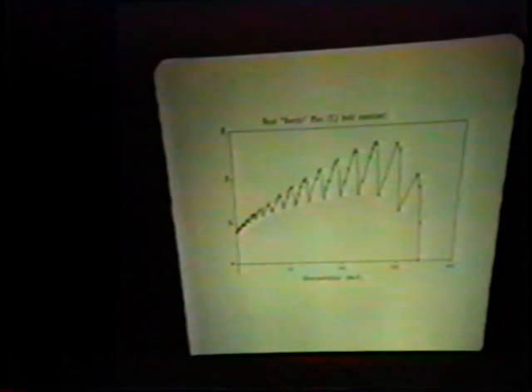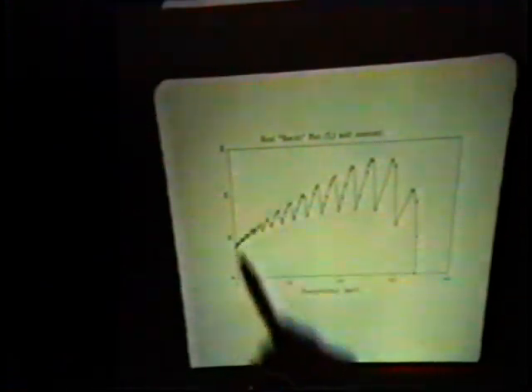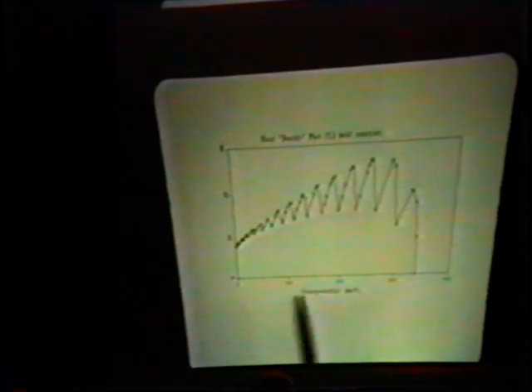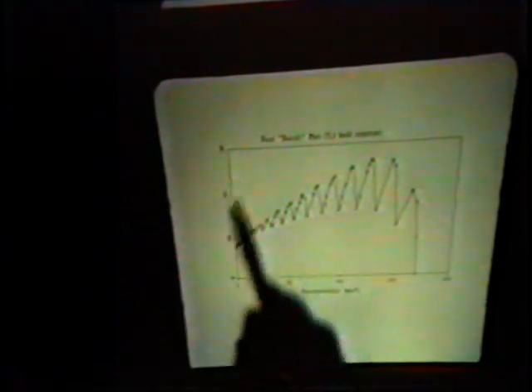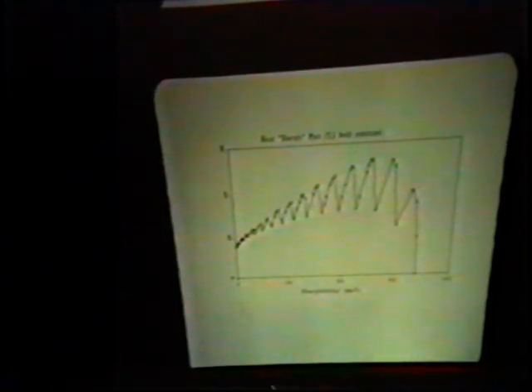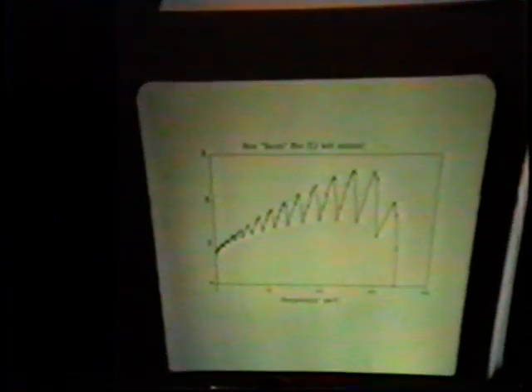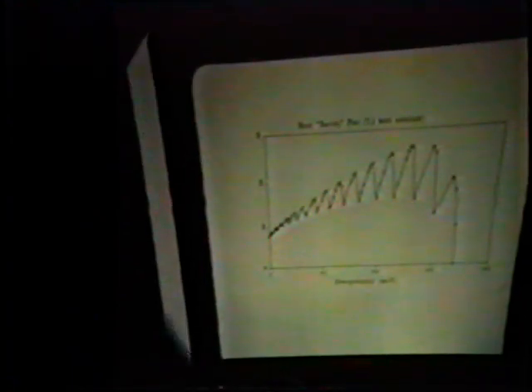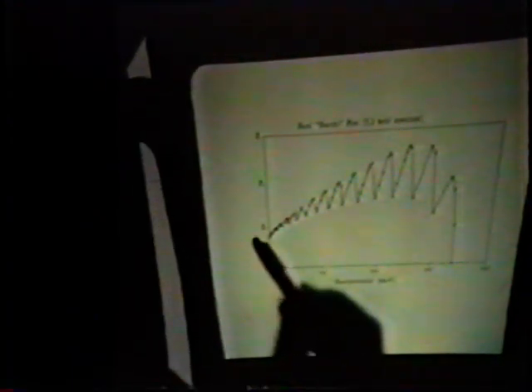So you can see this thing oscillates. I'm going to go very fast now. Okay, this thing oscillates. How can we account for that? Well, with TRM, if you look back at that paper of mine, I have a curve which looks like this. This is a curve of the heat, okay, the excess power versus overpotential. If the overpotential were changing in time, say linearly, then this would be a curve of overpotential versus time. What I think is happening with this curve right here, where we aren't seeing the excess power start from around zero back here and climb up, is that we are going up here on the edge of this thing. We are starting to climb, and eventually we reach a sort of a maximum height, and then we start to go downhill. And you can see with this thing, we start to go downhill here. This would eventually end up down here somewhere.